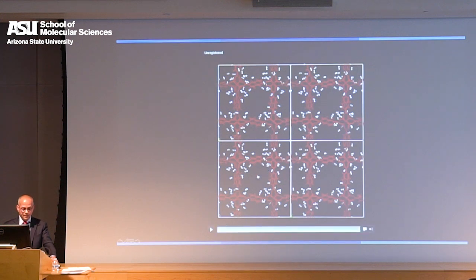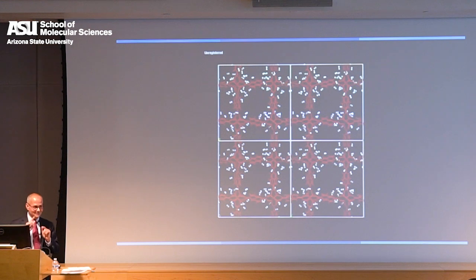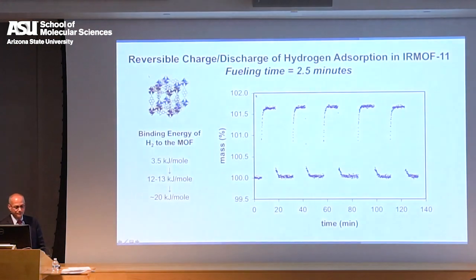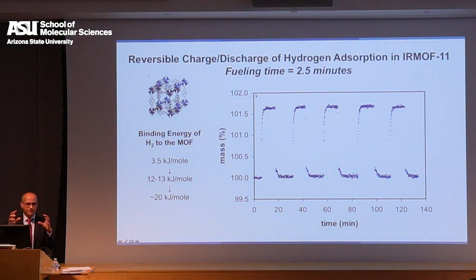Except that you have open space here that's not doing you any good, right? That's open space, so your fuel tank is going to be so much larger because you have this open space. But reticular chemistry can fix this because we know how to design materials that could self-catenate. Again, enumerated by Michael O'Keeffe. And that's this structure. You could fill that space by having two independent frameworks come together and mechanically fill each other. That way now I have introduced more adsorptive sites. I doubled my adsorptive sites per unit volume.